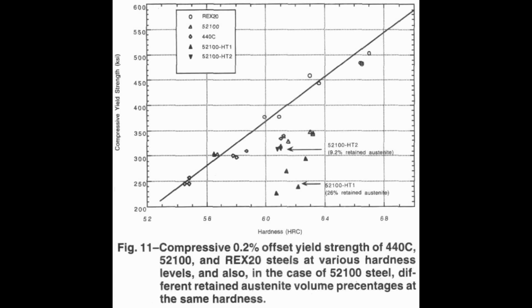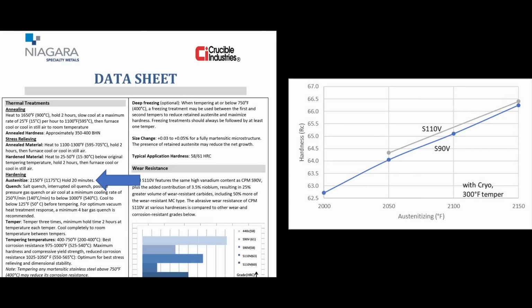High retained austenite also makes steel behave as if it is softer than it is. Two knives with the same hardness will behave differently if one has significantly more retained austenite than the other. So the steel will deform more easily. It will behave as if it is softer. So the edges will deform more easily, even though it's at the same hardness. With proper selection of austenitizing temperature and cryoprocessing, retained austenite can be limited to levels where it doesn't affect the performance of the knife. Some steels have more issues than others. For example, I found that the datasheet recommended austenitizing temperature for CPM S110V is very high, probably too high.